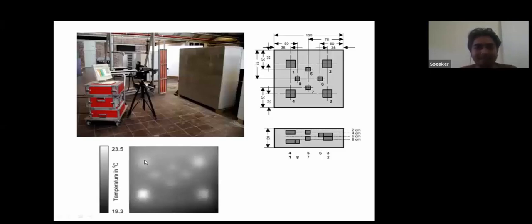Still, you can see it vaguely red too. So what conclusion can we draw here? We can say that the thermal camera can detect a defect up to 10 centimeters. So you can see here this is 2 centimeter, 4, 6, 8, and up to 10 centimeters we can see any kind of void inside the concrete. That's the power of this thermal camera.